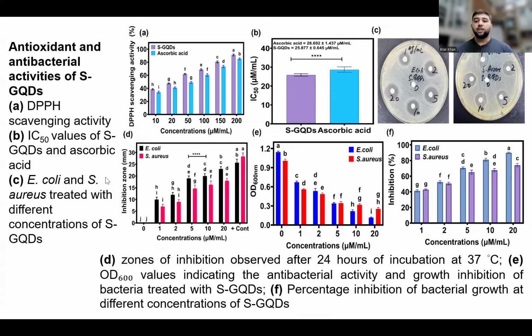The bacterial growth of the E. coli was more suppressed by the sulfur-doped graphene quantum dots compared to the gram-positive multi-drug resistant Staphylococcus aureus. And inhibition efficiency was around 90 to 95% for the E. coli at 20 micrograms per ml, and also 80% for Staphylococcus aureus. So it was good antibacterial activity.